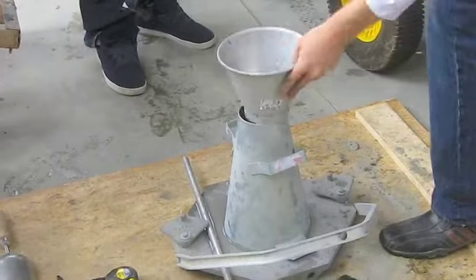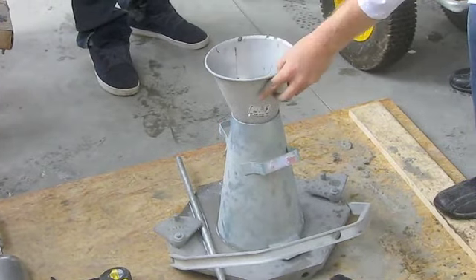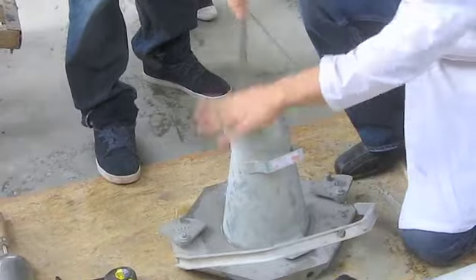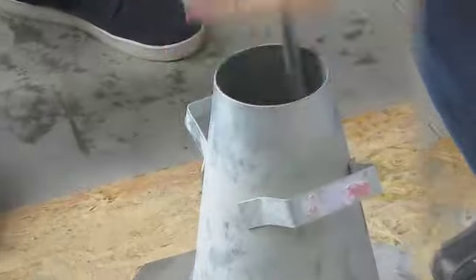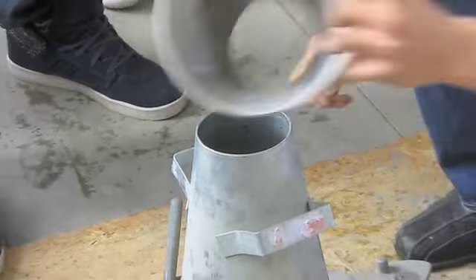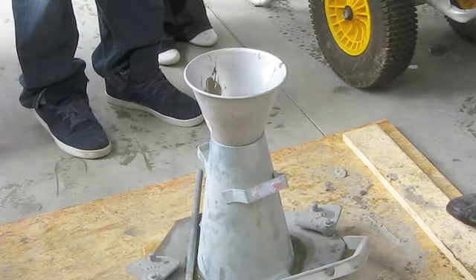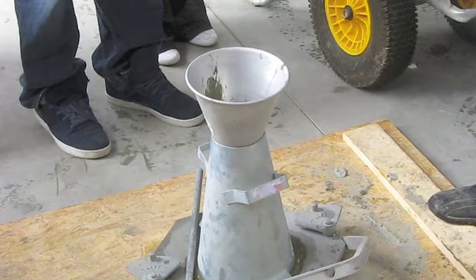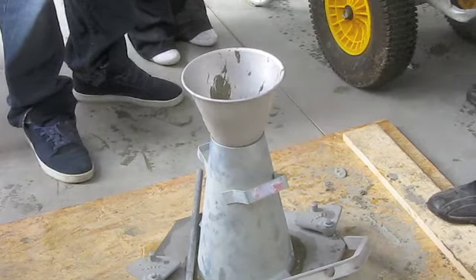Then, start adding concrete. You want to fill up the bottom third, and then take the large tamping rod and tamp 25 times. You want to complete the same procedure for the middle lift, again adding a third and tamping 25 times with the tamping rod.